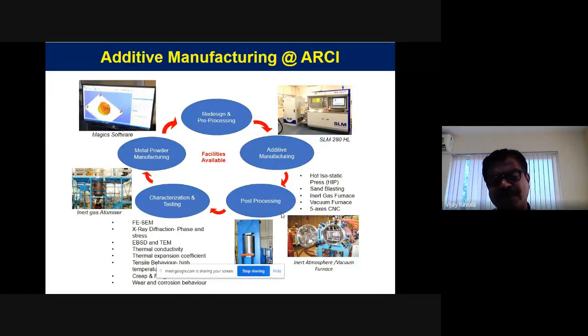So we also have a powder manufacturing facility. And once we have a powder, then from the model, you put it into the machine and manufacture the component. You can also do the post-processing of the material, because post-processing is very important. This is a non-equilibrium process, with very rapid cooling, quenching taking place, because the material which is being melted is around 100 microns or 50 microns or 40 microns, and then it gets cooled very fast. The cooling rates are very high. So that means it's like a quenching process.